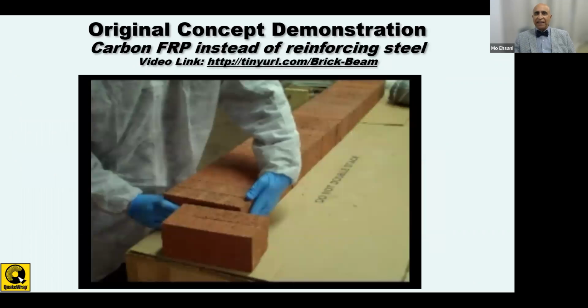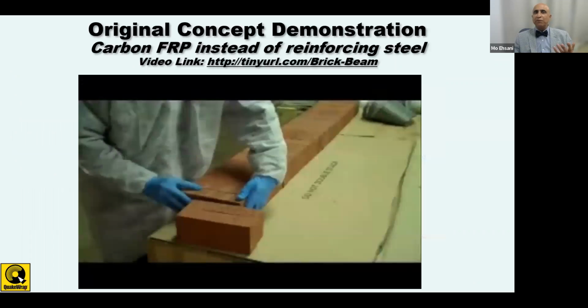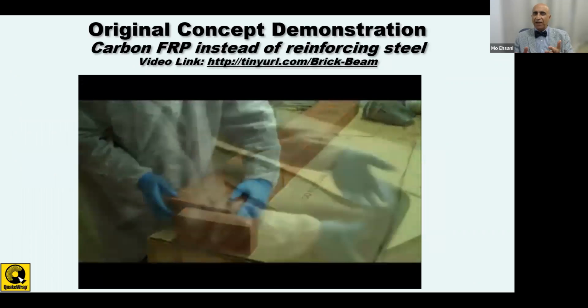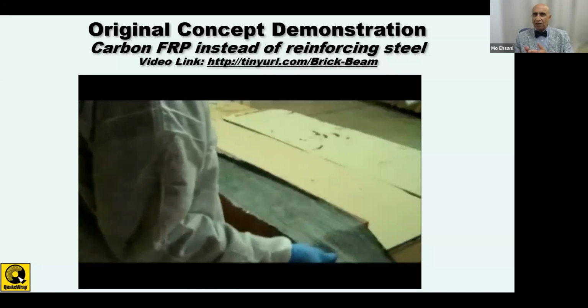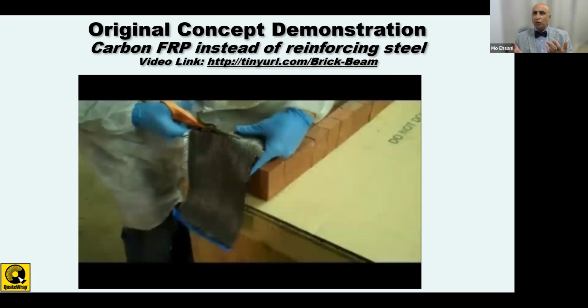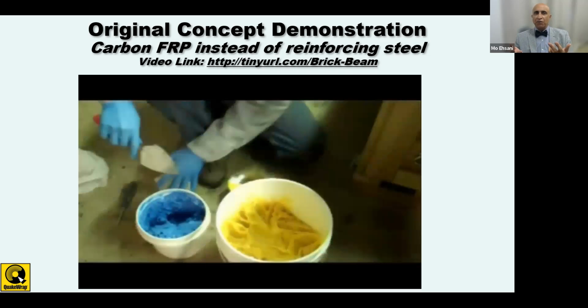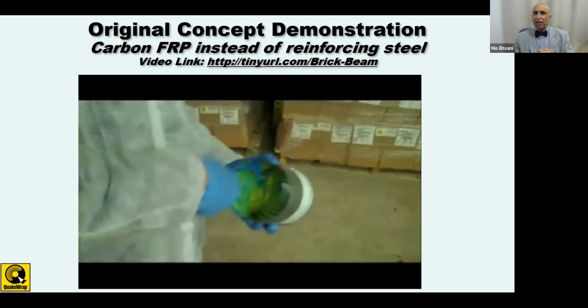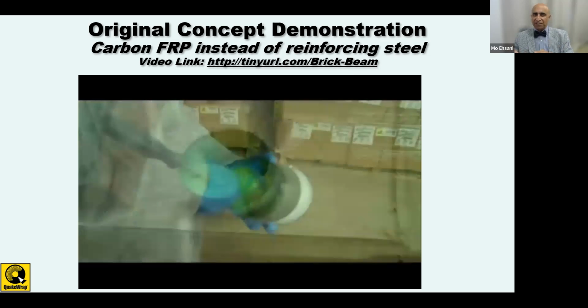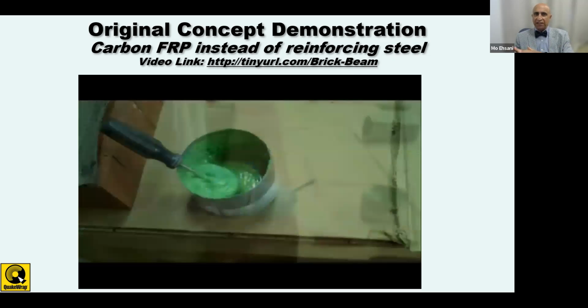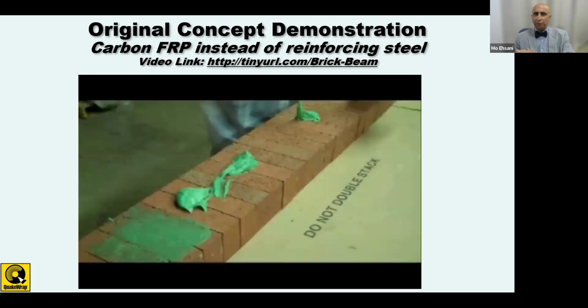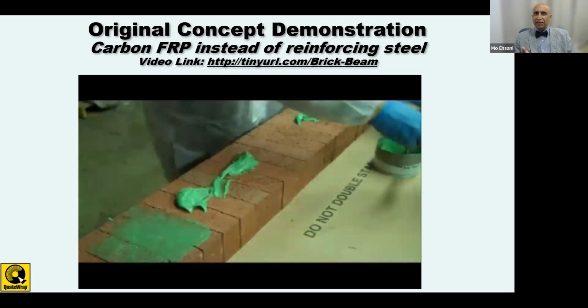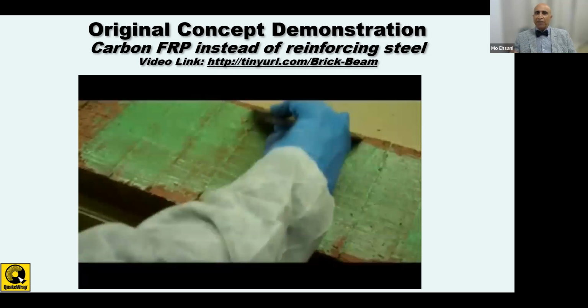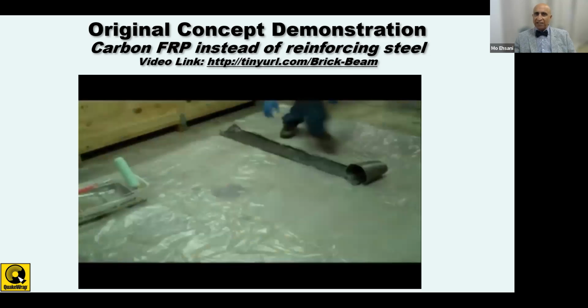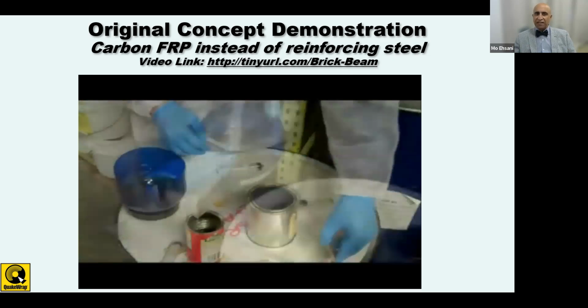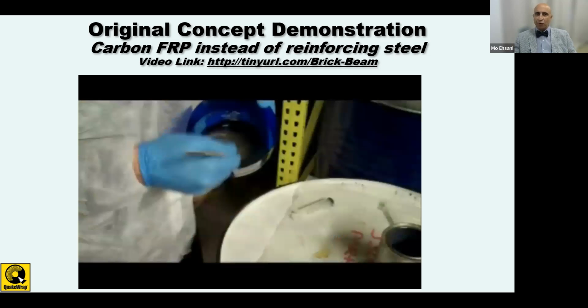So the basic concept of this can be shown in this video. Let's say here we have several bricks with no mortar between them, and we try to make a beam out of them. So we mix this particular epoxy, which is like a tack coat paste material. We put it on the back of the bricks to make it smooth and get rid of any of the sharp edges. Then the carbon fabric is saturated with this other resin, which has a consistency like warm honey.